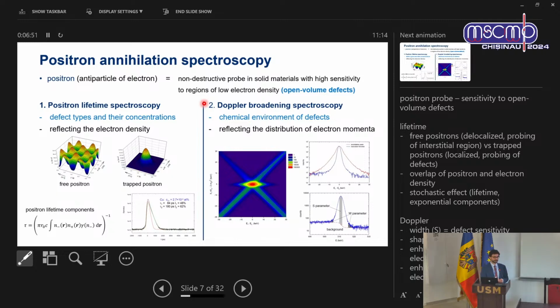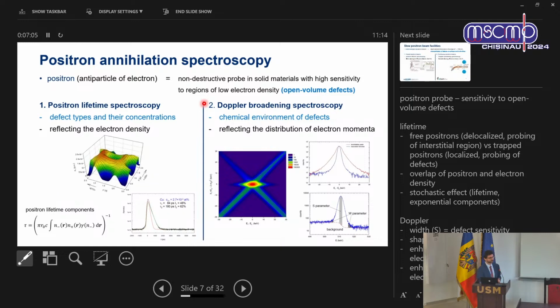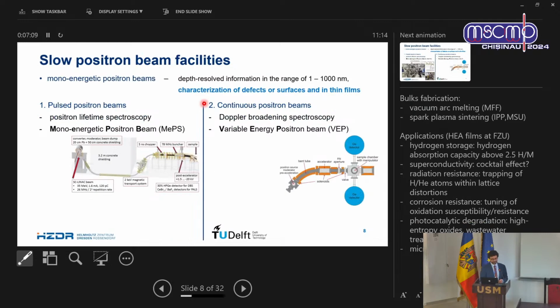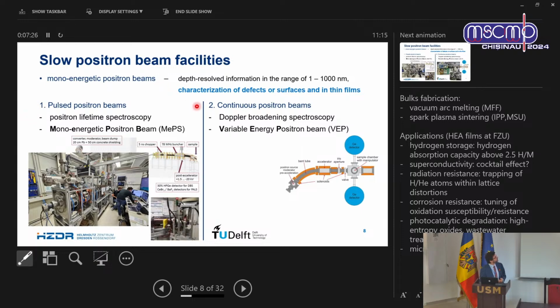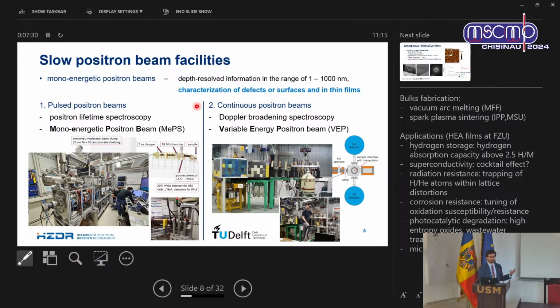However, this positron annihilation spectroscopy was originally designed for bulk materials, not for thin films. So in, let's say, the last 20, 25 years, new types of slow positron beams were developed. Either you can use the pulsed positron beams with an excellent time resolution to study the lifetime, or continuous positron beams to study the Doppler broadening spectroscopy and the energy variations of positrons. It enables you to study defects in thin films of thicknesses from, let's say, 1 nanometer to 1 micron. So now let's get to the results of our thin films deposited by magnetron sputtering.